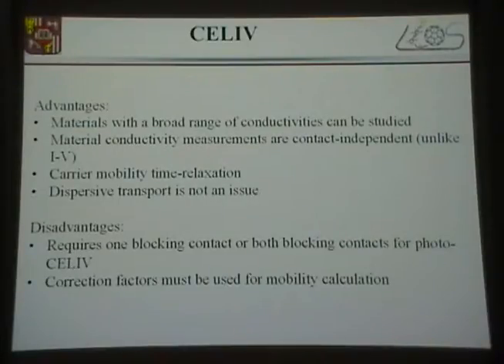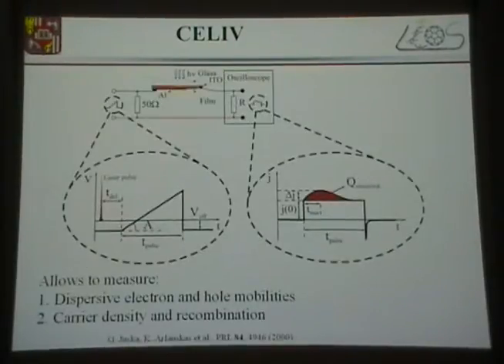You can also measure the carrier mobility as a function of time, so this charge being dispersive. This is in principle the only method I know which can give you access to the mobility time dependence. One of the disadvantages, I will also briefly show, is that some rather complicated correction factors must be used when you calculate the mobility from the CELIV.